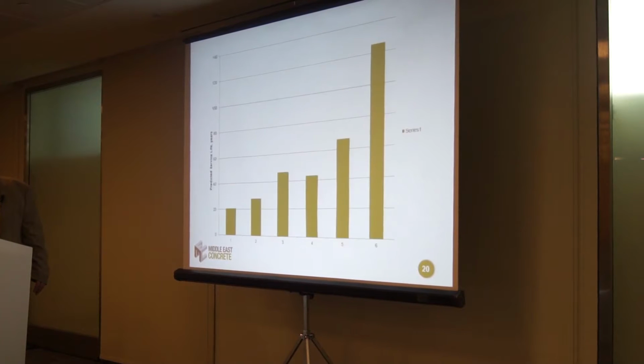So we can see on this particular model, we used a 0.35 plain cement mix, plain Portland cement mix, no supplementary cementitious material. That was our base mix. I'll go ahead and change to the next page. So, 100% cement, no supplementary cementitious material. The model predicted that the service life of that concrete was 20 years. 20-year concrete, I don't know too many engineers or owners that would be happy with concrete that was only expected to last 20 years.